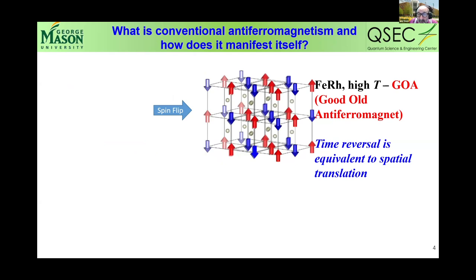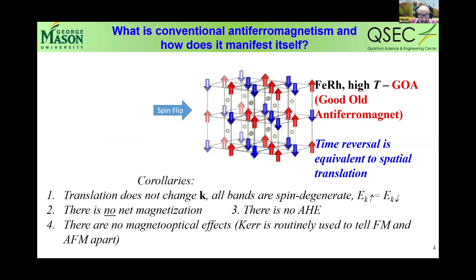And because obviously the spatial translation doesn't change electronic structure in the momentum space, you can say that all bands should be spin degenerate everywhere. But obviously there is no net magnetization and there is no anomalous Hall effect and no magneto-optical effects. Now these, you can also call them, if you want, Néel antiferromagnets, because those were antiferromagnets that were initially